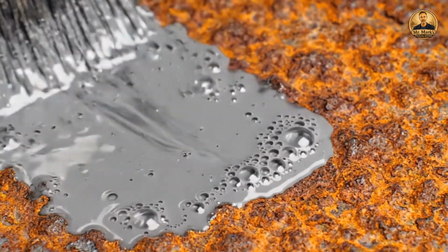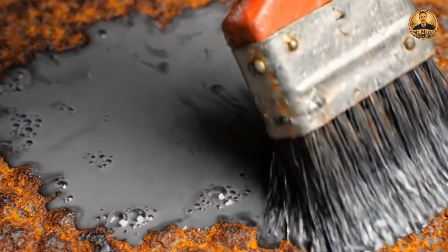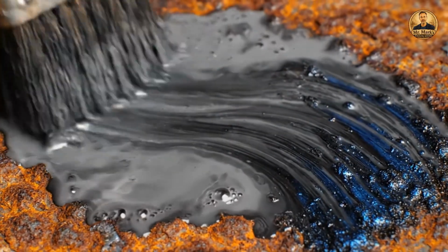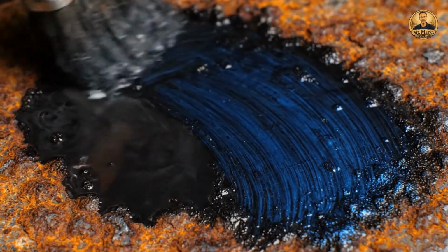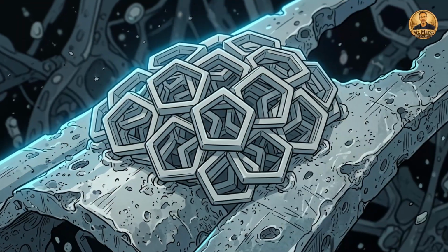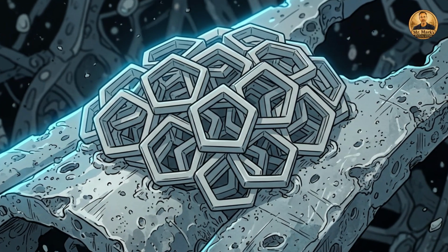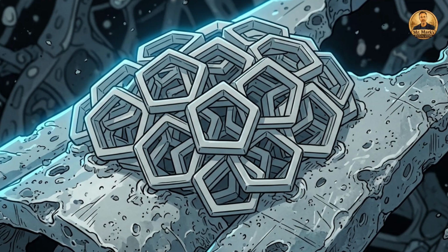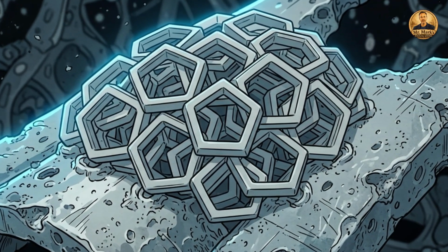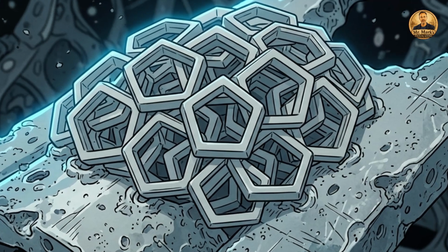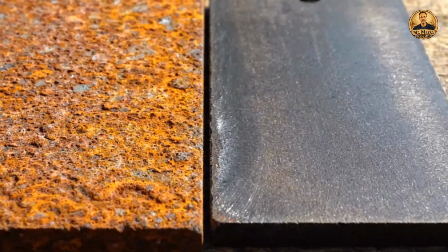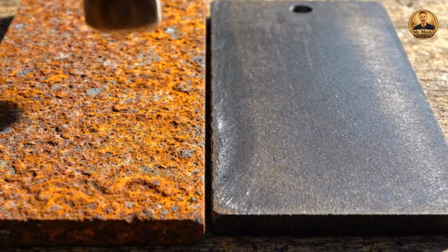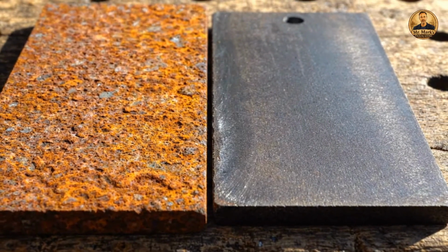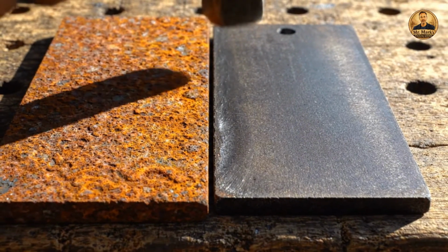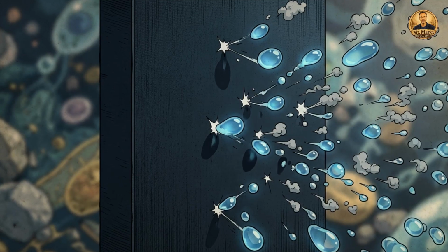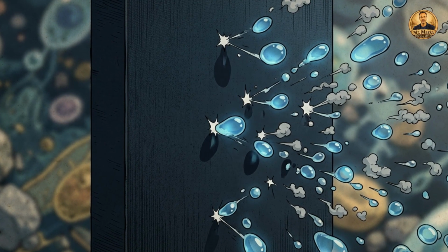When you apply a tannic acid solution to rusted steel at the right pH, around 2.2, those phenolic groups release oxygen anions that lock directly onto the iron ions inside the rust layer. They form what chemists call 5-membered ring coordination complexes, bonding 1-to-1 with Fe2+ ions and 3-to-1 with Fe3+ ions. The result is a new compound called ferric tannate, dark blue-black, insoluble in water, bonded directly to the steel surface at a molecular level, not sitting on top of the rust, not sealing over it, replacing it, molecule by molecule, with something stable and protective.